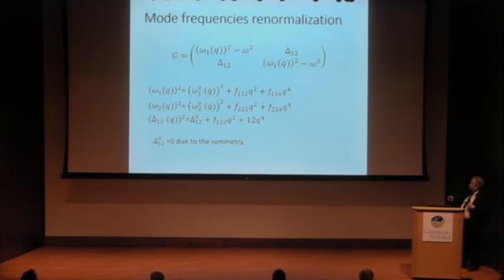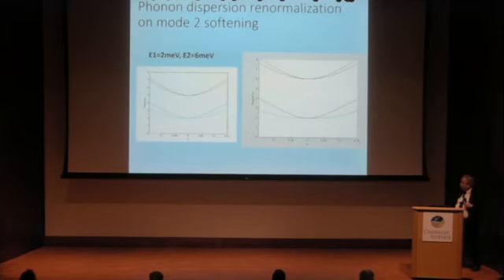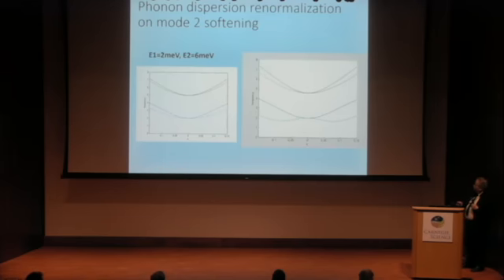So now we use a very simple formulation to look at how the mode frequency could be renormalized. I forget for the moment about the imaginary part of the coupling, just the renormalization. Let's have a look at what can happen. We consider two modes, one with frequency at the endpoint of 2 millielectron volts, the other 6 millielectron volts, and we see very weak coupling, very weak shifts of the position. But look here, what happens if the second mode goes down? It goes down, down, down, and finally it can easily create a situation where we have an instability at finite Q. The situation is very similar to that close to the gamma point.